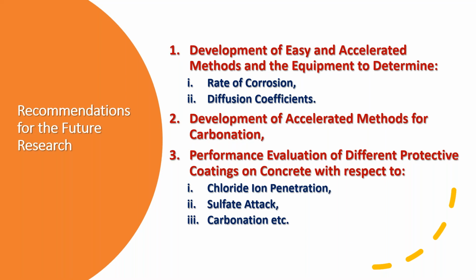The solution is that we have to understand the mechanism of this acid attack. You know that the pH of the concrete will be between 13 and 11, whereas the pH of the sewage water will be 4 or 5. At the interface, what will happen? At the interface between the sewage water and the concrete, the concrete tries to neutralize the pH. And in order to neutralize the pH, it will release a certain amount of calcium hydroxide. So in due course of time, because the leaching will take place, the concrete will become porous because of this acidic attack. So what is the remedy?